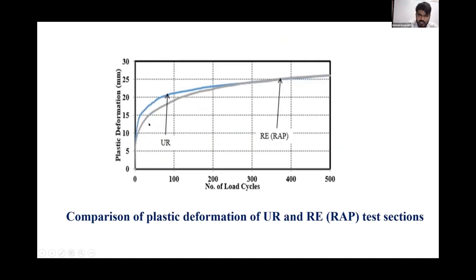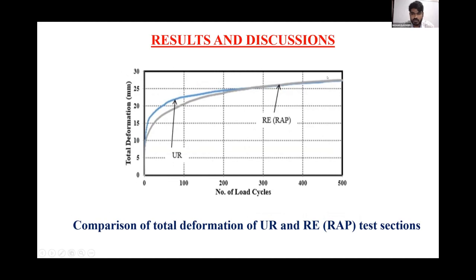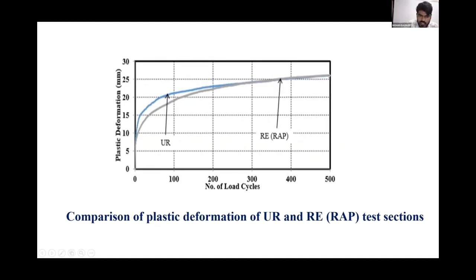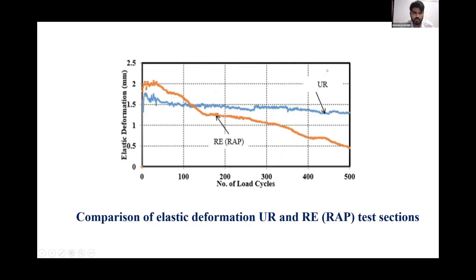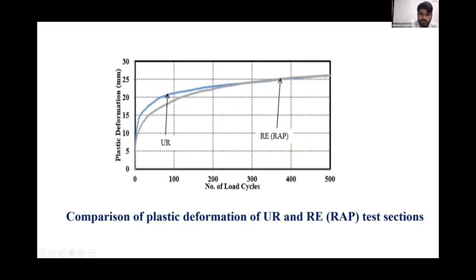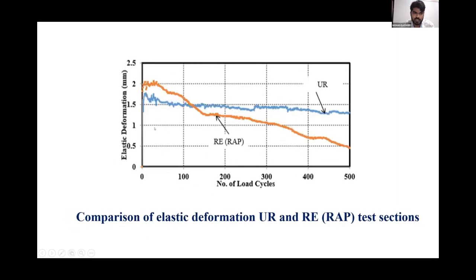Next, plastic deformation. Here, the total plastic deformation observed is 26 mm. Total deformation was 27 mm and plastic deformation was 26 mm. More than 90 to 95% of the total deformation constitutes plastic deformation. Only 1.2 mm, that is roughly 5% of the total deformation, is elastic. Here also the same trend is observed as in the case of total deformation. This is the elastic deformation observed in the case of unreinforced and reinforced sections. Here, no significant changes were observed due to the geocell confinement, geocell reinforcement.